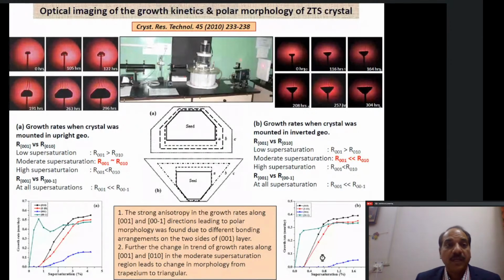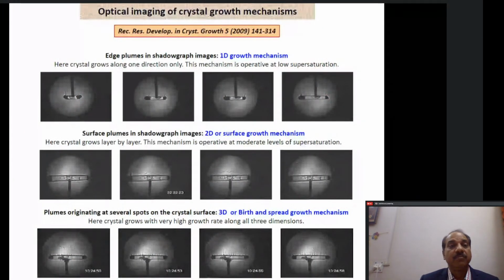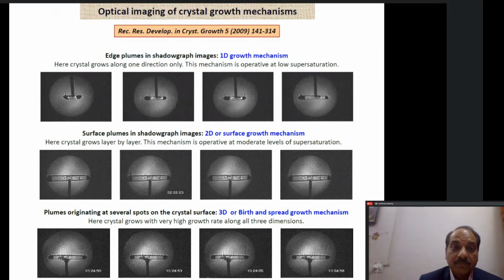And now this is again in KDP crystal. We did experiments to find out what happens when we grow this crystal under different conditions of supersaturation. When we were growing this crystal under low supersaturation conditions, we were able to see that the crystal is growing only along one dimension. So basically it was elongated along X and Y direction only. There was no fattening of the crystal taking place. And that was clear from the plumes which were visible from the edges of the crystal.